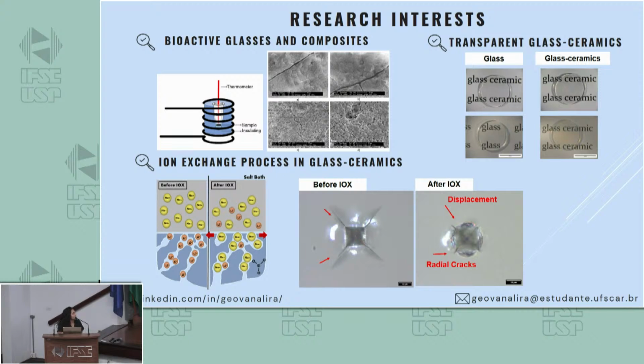As you can see in this figure, ion exchange is a very useful technique for improving the mechanical properties of glass or glass ceramics. It's used in the famous Gorilla Glass for improving the mechanical properties of this material. This process involves the exchange of small ions from the glass surface or glass ceramic surface with the larger ones from the molten salt bath. And the difference between the ion size results in a residual compressive stress on the glass or glass ceramic surface, and this residual stress enhances the mechanical properties in these materials. So this is my thesis subject.